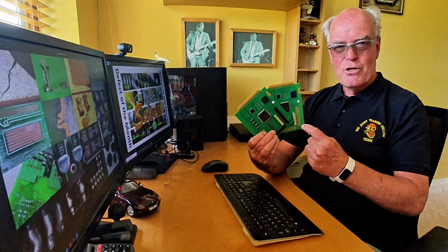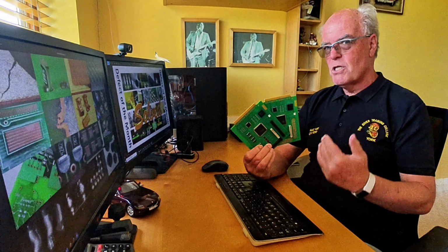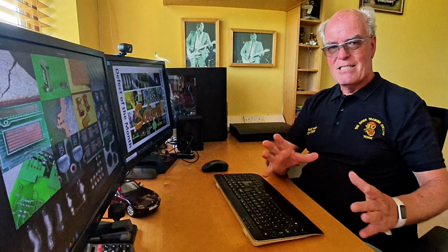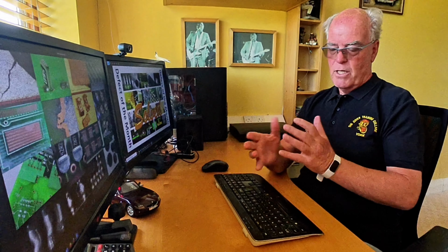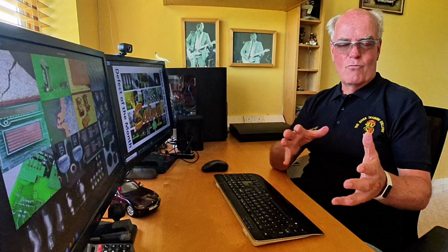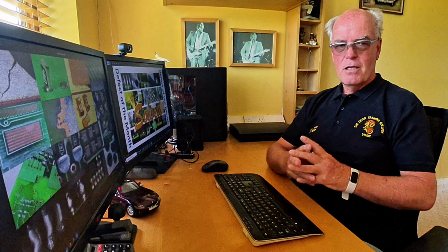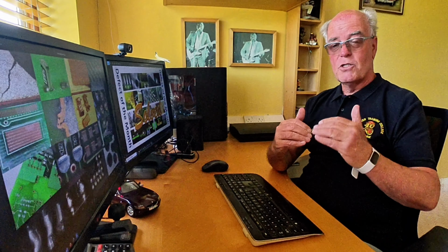These have all got test circuits directly underneath the components, which allows us to assess residues that might be left behind because you're running a no-clean process, or if you are cleaning, it demonstrates whether you've been successful in removing all the material from underneath the packages by measuring the SIR, or the change in SIR between a clean and a no clean, and perhaps a raw board, a basic board that has not been subjected to any other operations. So condensation testing condenses moisture onto the surface.